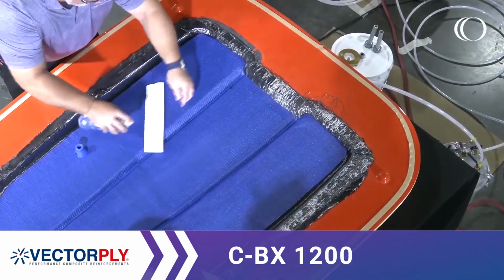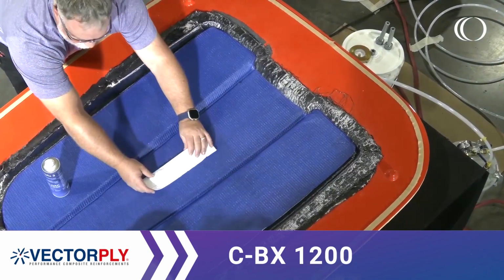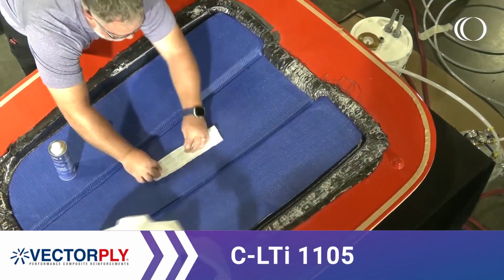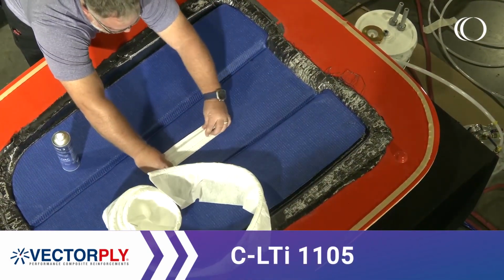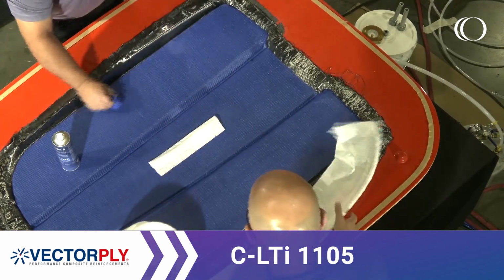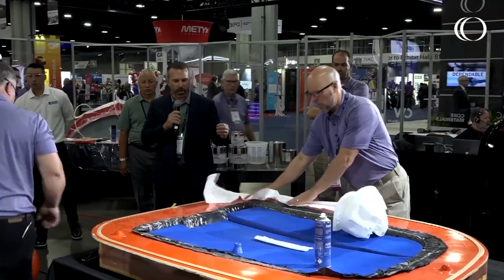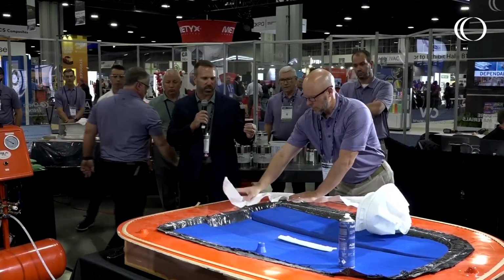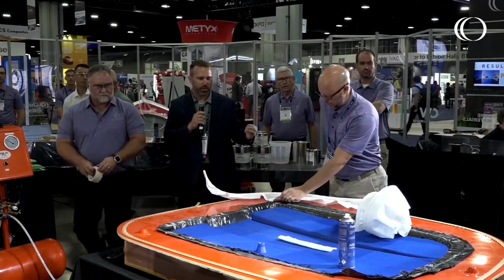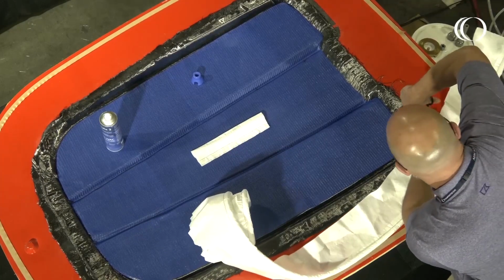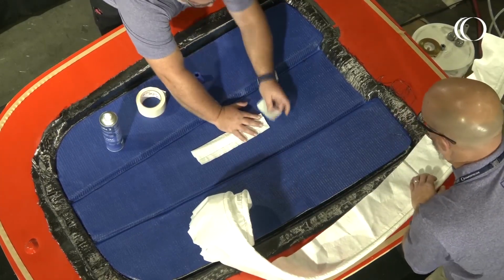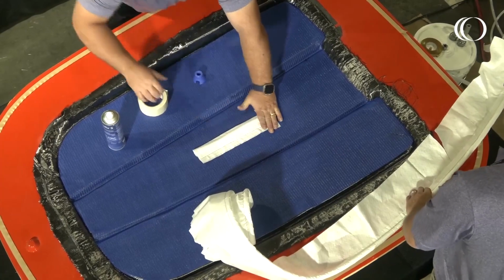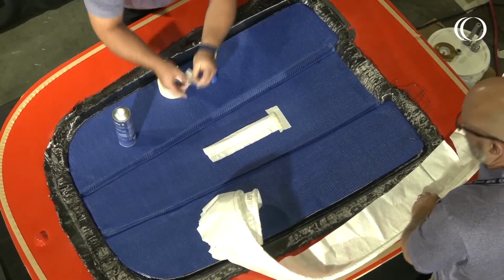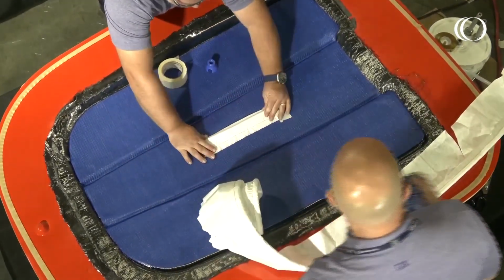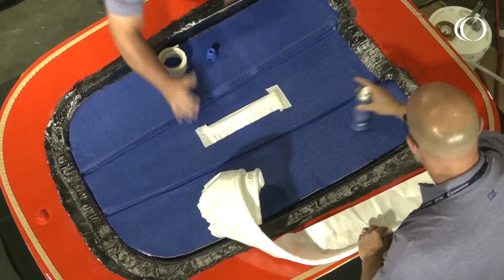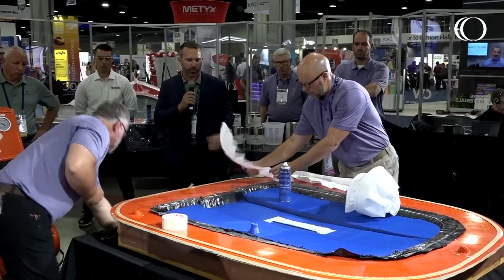And then backing that after the core is CLTi 1105. And the 05 has a mesh in it. It really is designed for two things, really for better cuttability, but the most important thing is just the resin encapsulation around the fibers. We were talking about earlier how the permeability of carbon is a lot less than the glass, and so this just gives it an extra insurance knowing that the fibers are completely wet out. It can be a challenge under core like this sometimes if resin flows too fast, and that just gives you the insurance knowing that it's fully wet out.